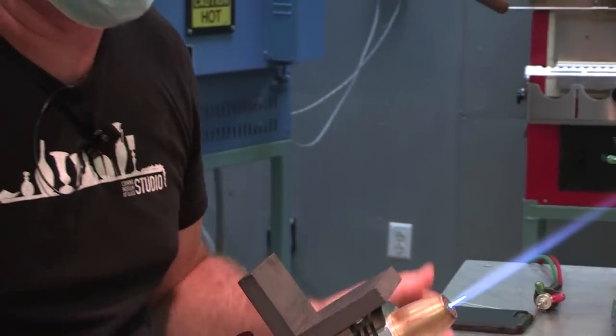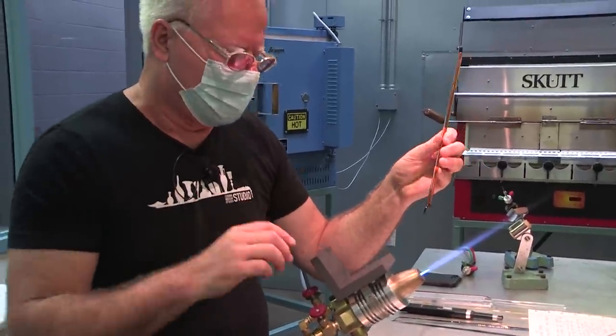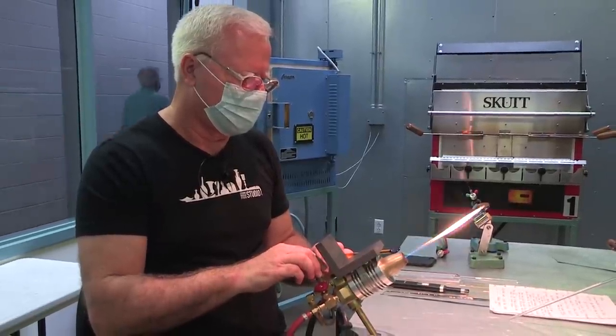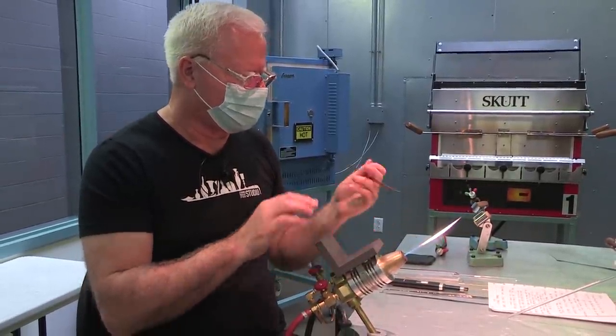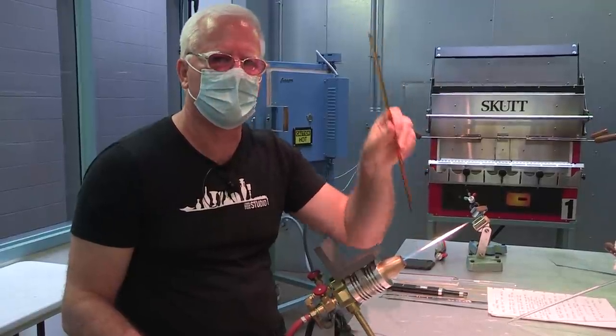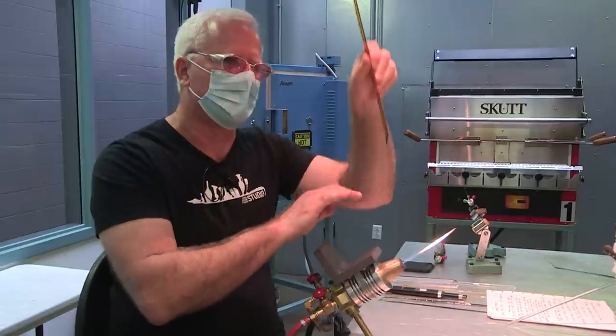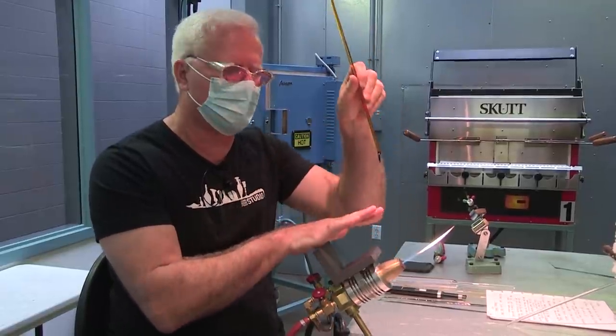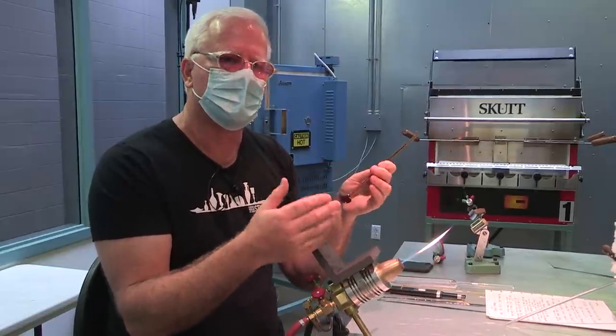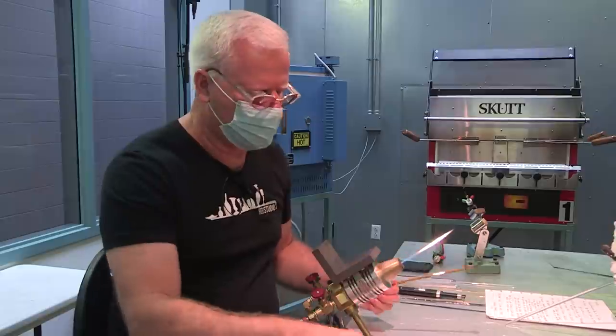Another popular mistake, or change with the results, if you are in your reducing flame and you're trying to get that color to happen and shift, is bobbing in and out, right? Taking it in and out. So instead of having a consistent application of the color, you get a flash of color and then a flash of cool and a flash of heat and a flash of cool. And it doesn't actually ever move into those purples. And the third most common situation is a situation like this.